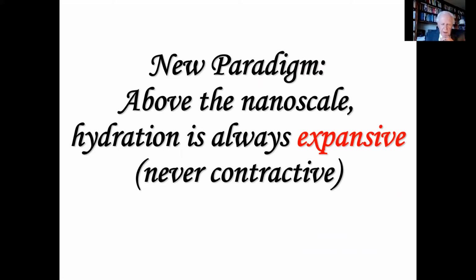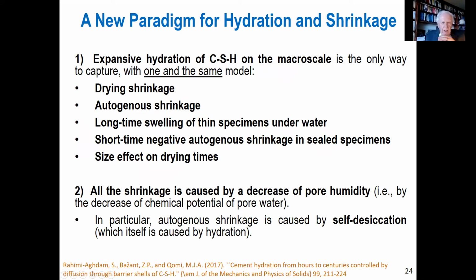And now I come to an inference from this. It took some time to construct. It was generally believed that cement and concrete always contract, that hydration is contractive. But that's true only on the nanoscale. The conclusion is that hydration on the scale of many micrometers, up to 1 millimeter, is expansive, always expansive, and all the shrinkage that we see is due to self-desiccation or drying. Both decrease humidity, and that's one phenomenon, drying. All right, so I could say that's a new paradigm for hydration shrinkage.